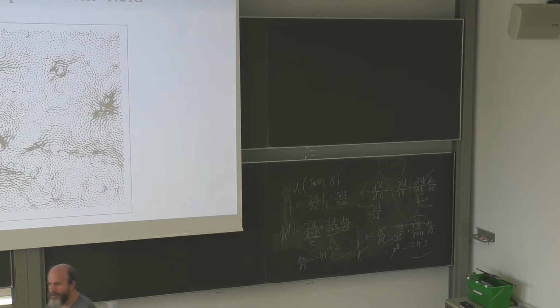And the whole point is that non-affinity softens, it changes the modulus, it causes softening, because in fact, simply the point is that if you shear homogeneously, affinely, you're not in a minimum. And so you minimize a bit, your energy drops, and the curvature is a bit weaker, and it means that your system is a bit softer than predicted by the affine response.